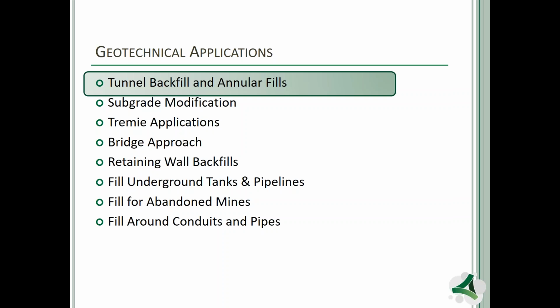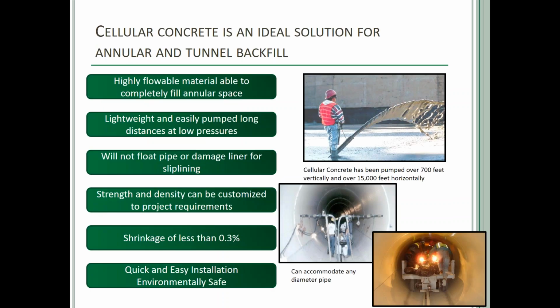When doing annular fills and tunnel backfills, it's extremely important to remember that the material, when being placed, gets extremely fluid, so it will go into every nook and cranny that it can find. It's also important to remember that this material is pumped under extremely low pressures so that you will not run into a floating pipe or damaged lining, those slip lining projects. And the shrinkage of the material is less than 0.3%. So you've got a tremendous amount of advantages on various projects out there.